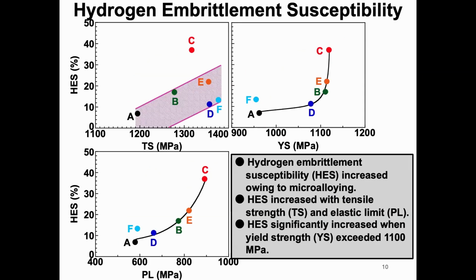This figure shows the relationship between hydrogen embrittlement susceptibility, HES, and tensile strength, yield strength, and elastic limit. The hydrogen embrittlement susceptibility increased by the addition of alloying element, and HES increased with increasing tensile strength and elastic limit. In addition, HES significantly increased when yield strength exceeded 1100 megapascal.